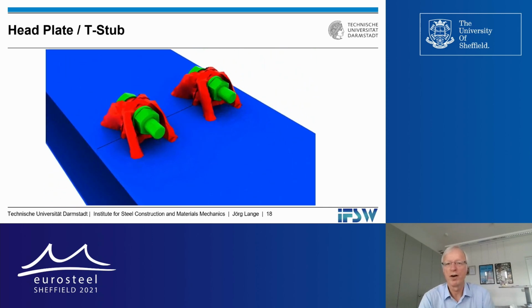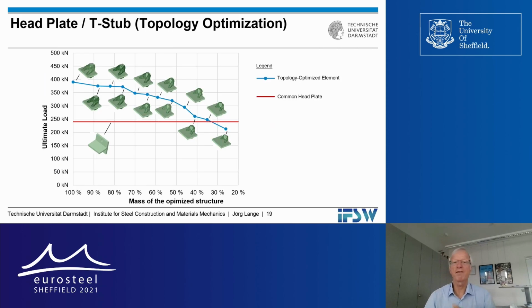We printed the red structure onto the flange on the top and lower side of the top flange. And afterwards, we can bolt it with normal bolts that are loaded under tension. So it's a replacement of the head plate. And in this third step, in this topology optimization, we get a totally new structure. We don't replace a stiffener by a new stiffener. And you see here in this red structure, you get little tension legs. So it's not the bended T-stub as we know it from a head plate connection, but we get more tension, less bending.